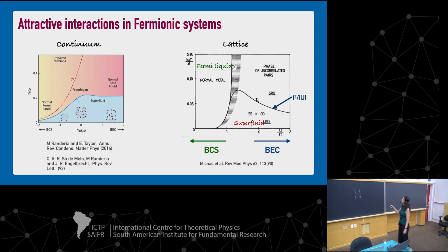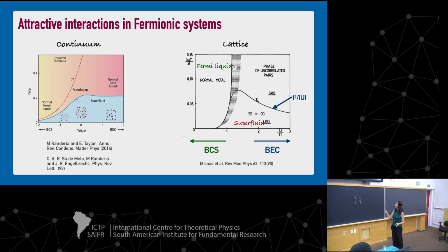So here you also have a normal metal from which, when you decrease the temperature, you enter the superfluid phase. So you have both things happening at the same time. The pairs form and condense all together, and this is, once again, what we call the BCS regime. And here you have a phase where this T_P is the pairing temperature, where we have pairs forming. And then in this region, you have this phase of uncorrelated pairs, and you decrease the temperature. It falls with t squared over U, and you enter the superfluid region with preformed pairs. And this is what we call the BEC region. So regulating the intensity of the interaction, you can go from one region to the other.